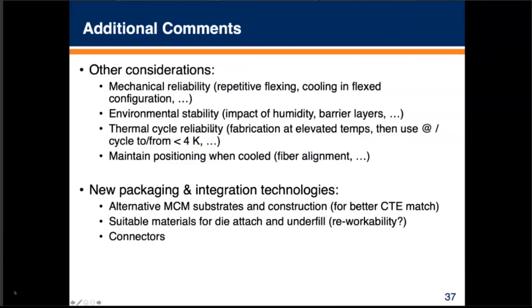There's also thermal cycle reliability. One of the big challenges is that we're fabricating these at elevated temperatures and we're cycling down to and from 4K or even lower. So the thermal cycle reliability is certainly important. Other considerations, not necessarily for the superconducting flex cables, but if you were doing something with photonics, there's other considerations like having fibers aligned properly and maintaining that alignment as you cool off as well. All the CTE types of things that I'm sure people in the packaging society totally comprehend.